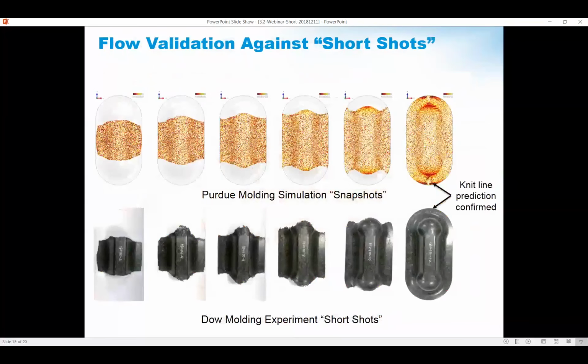Let's take a look at time-lapse shots, so to speak, of the simulation on the top, and then short shots on the bottom where the folks at Ford and Dow have stopped the press using different thickness spacers to give us short shots as an experimental confirmation of the predicted flow pattern. And I'll note the simulation was performed long before the short shots were executed. When we saw the short shots, we were jumping up and down at how well those flow patterns agreed with each other. And you'll note that there's a knit line prediction that is confirmed in the experiment in the way that those flow fronts come together.